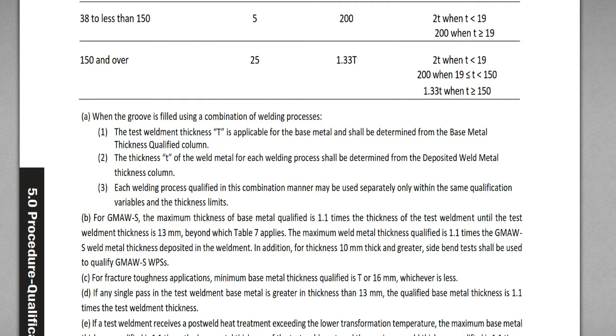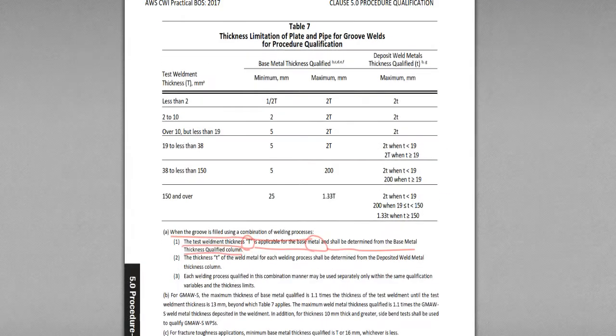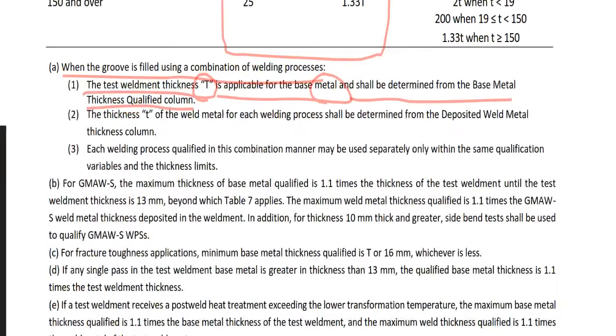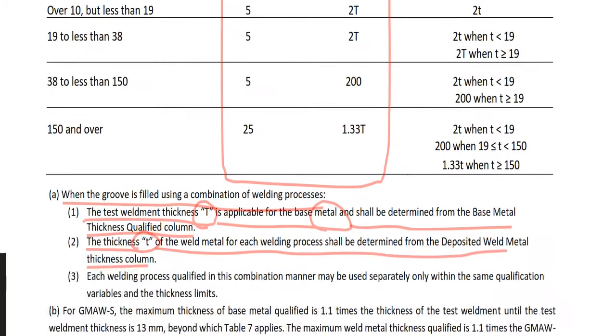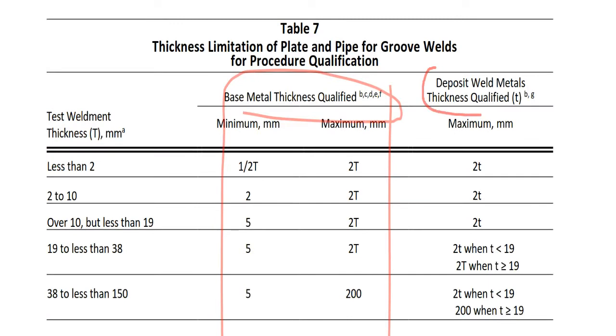Note A. When the groove is filled using a combination of welding processes, number one, the test weldment thickness, capital T, is applicable for base metal. Base metal thickness should be determined from the base metal thickness qualified column, which is here. And number two, thickness, the lowercase t of weld metal for each welding process should be determined from the deposit weld metal thickness qualified column. And this means here, deposit weld metal thickness qualified, lowercase t.